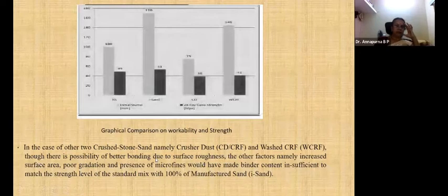In the case of the other two crushed stone sands, namely crushed dust and washed crushed dust, though there is a possibility of better bonding due to surface roughness, other factors, namely increased surface area, poor gradation, and presence of microfines, would have made the binder cement content insufficient to match the strength level of the standard mix with 100% manufactured sand. Because of that, the strength is lesser than the manufactured sand.